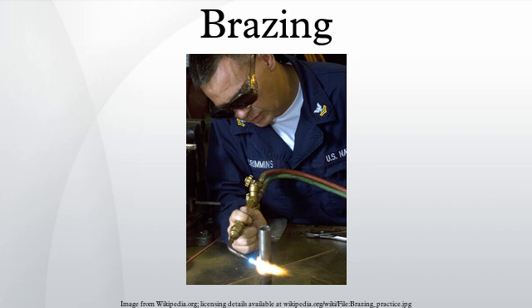Flux: in the case of brazing operations not contained within an inert or reducing atmosphere environment, flux is required to prevent oxides from forming while the metal is heated. The flux also serves the purpose of cleaning any contamination left on the brazing surfaces.